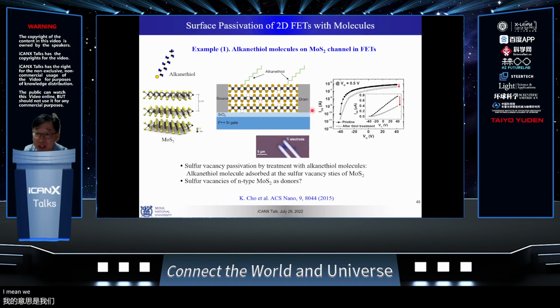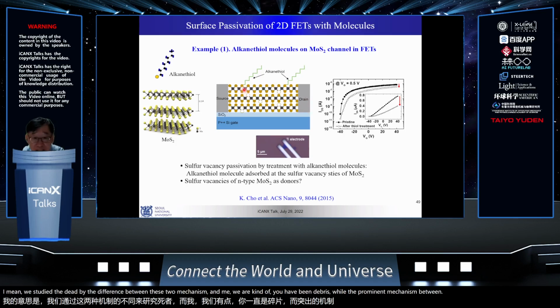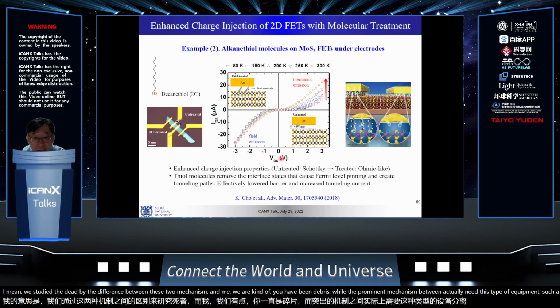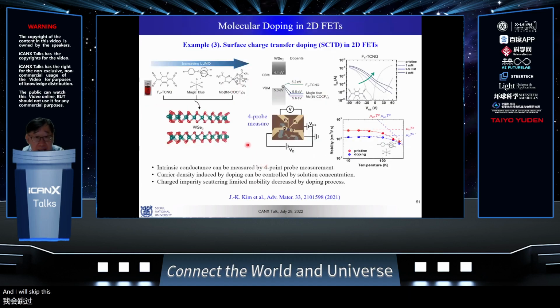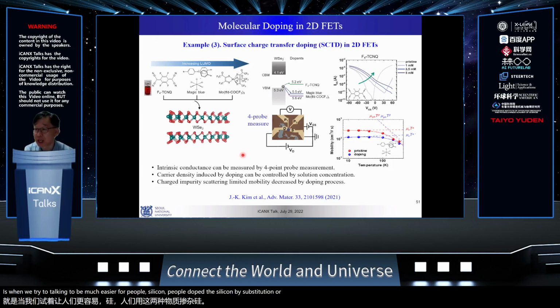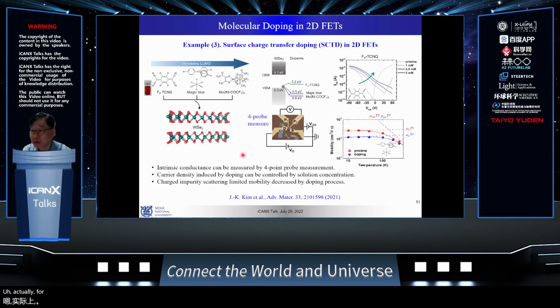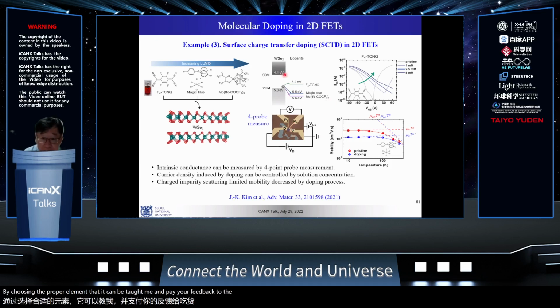So we studied the difference between these two mechanisms, and we interpreted what the dominant mechanism is, which is indeed the sulfur vacancy. And I will skip this part. Now, for 2D materials, the question is doping. People dope silicon by substitutional atoms, like depositing arsenic, column 3 or column 5 elements, and even gallium arsenide can be doped N-type or P-type by choosing the proper element. But 2D materials like WS2 or MoS2 are very difficult to dope in a substitutional way.